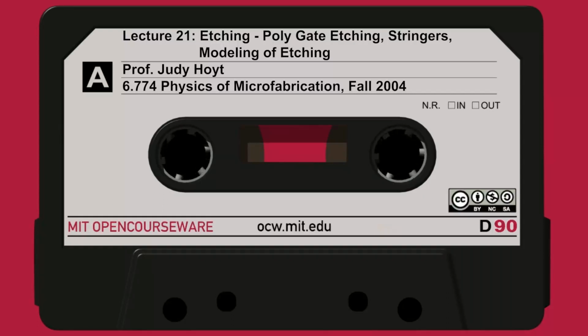But unless you have a long overetch that you do at the end of a step, you can get stringers left behind. Let's just show an example here. On the left, I'm showing where we've etched through polysilicon. There was no topography on the original part of the wafer, which is flat. So I have photoresist and I've etched polysilicon anisotropically. Everything looks very good. Now what's happened on the right? Well, on the right-hand side, I had some initial topography. So I had a step that looked like this, okay? As a result of having that step, the polysilicon overlayer, which is shown by this stippled region, the polysilicon went over everything, okay?